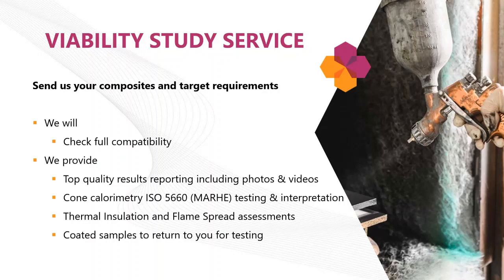So at the beginning, we will do screening. We will check the full compatibility with the basic tests, because adhesion is everything. If there's no adhesion, there's no fire protection. So that needs to be tested first. But if that's okay, we will provide cone calorimetry testing and interpretation. We can provide you top quality results, reporting, including photos, videos. We can do thermal insulation and flame spread testing. And after the testing, we can return those coated samples to you so that you can test if the composite is still valid. And of course, we can send you non-burned samples back to test if you want.